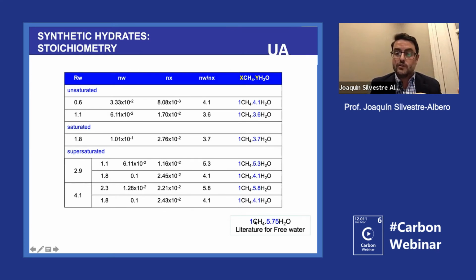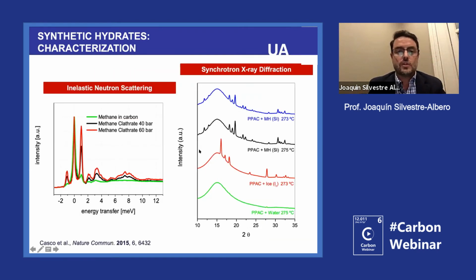You will know that the natural hydrate is 1 molecule of methane, 5.75 molecules of water. And you can see that at least in the samples where we have a significant amount of water, that means this 2.9 grams per gram and 4.1, you see that the stoichiometry is very similar. So that was anticipating that it looks like we are making gas hydrates in the cavities of the carbon. But then we wanted to be sure about this, so we did 2 experiments to confirm the nucleation of the hydrates. One is inelastic neutron scattering and synchrotron X-ray diffraction.